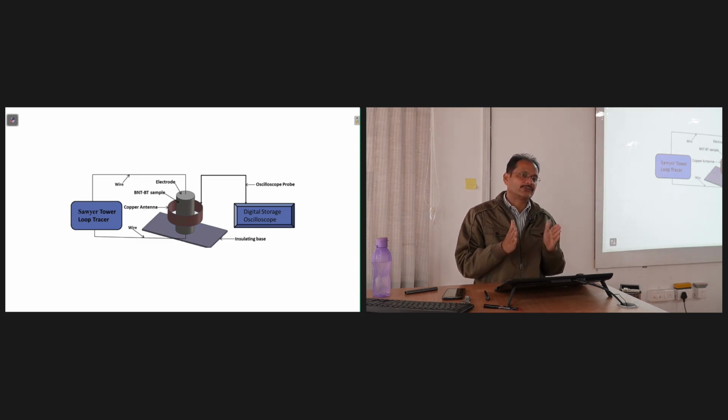So positive and negative dipole formation takes place. The barium or titanium ions remain positive, so oxygen will be negative, with some separation from their symmetric position. That leads to this dipole formation. Based on that, we considered the oscillations of dipoles, alternatingly.